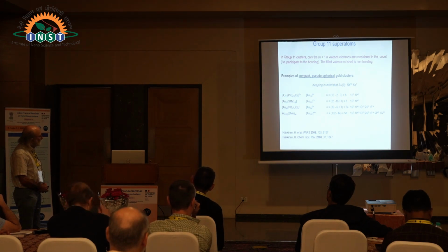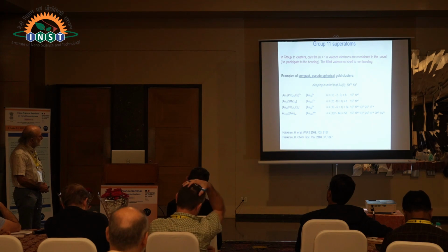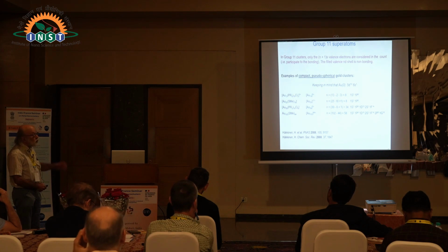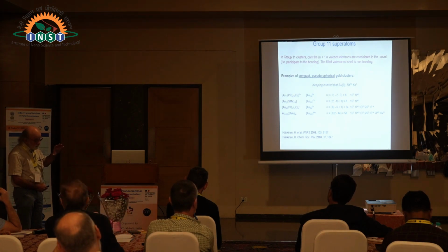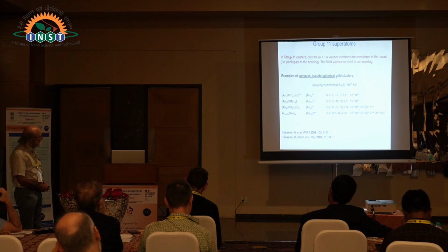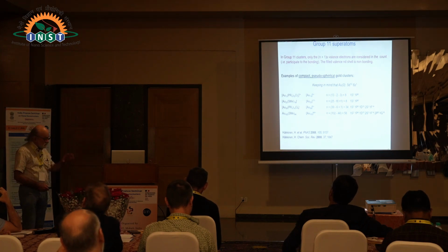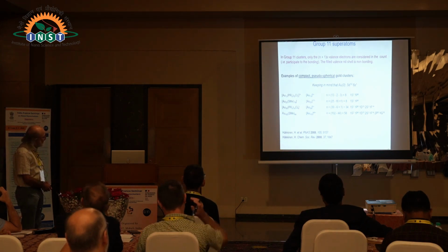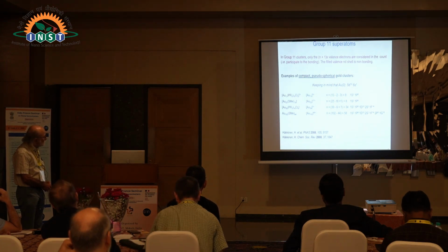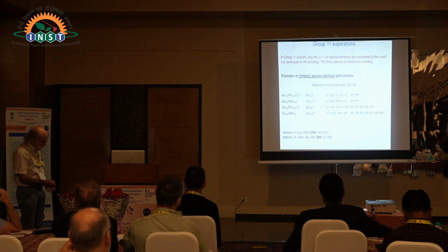Gold 13, so it means that if gold was 0, we would have 13 electrons, but we have 2 chlorides, oxidation state -1, so -2, and we have a +3 charge, so -3. So the result is 8 with this configuration. Looking at this one, for example, thiolate is formally -1, so we have 102 atoms of gold, so 102 minus 44, 58, and we have this closed shell configuration and so on.